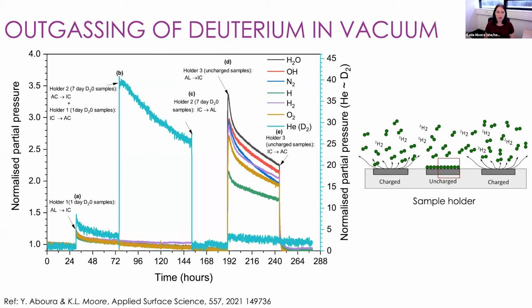So Yasser set up an experiment using what we have added to the NanoSIMS, which is called a residual gas analyzer. This residual gas analyzer allows us to look at the composition of the vacuum. Although we've got a very, very good vacuum, there are still some residual gases remaining in there. I'm not going to go through the whole of this graph, but I just want to highlight what is happening in this region here. Yasser did a series of experiments where he put sample holders in and out of the chamber that has the residual gas analyzer attached to it and looked to see how the deuterium concentration in the vacuum increased and decreased.